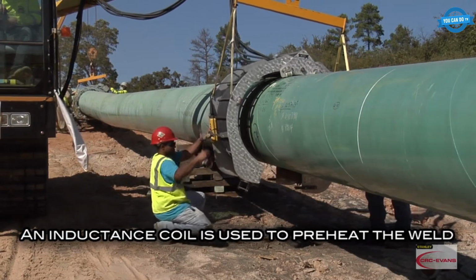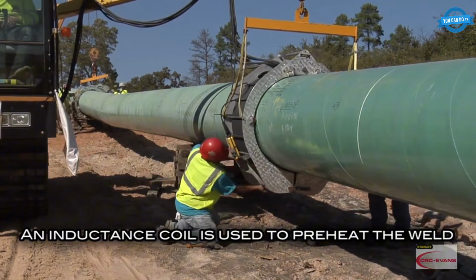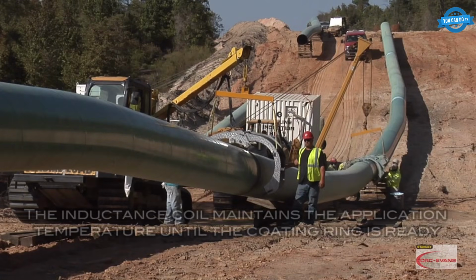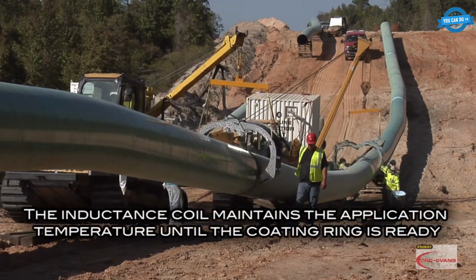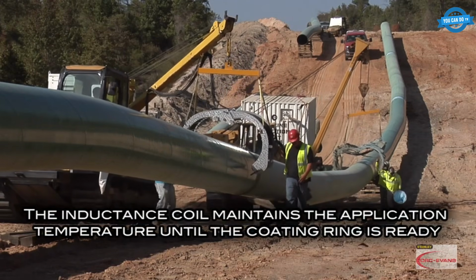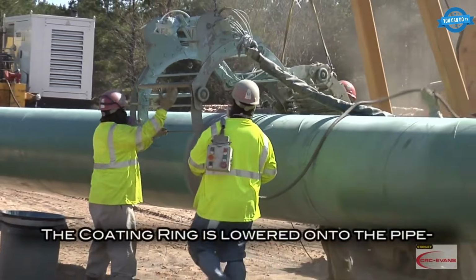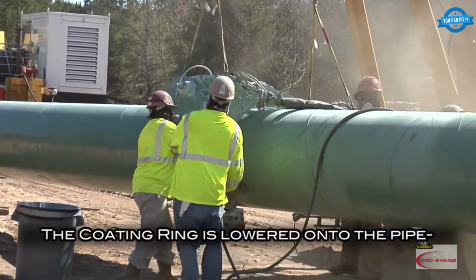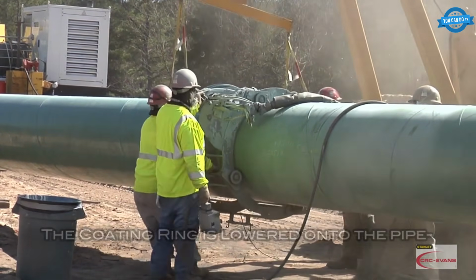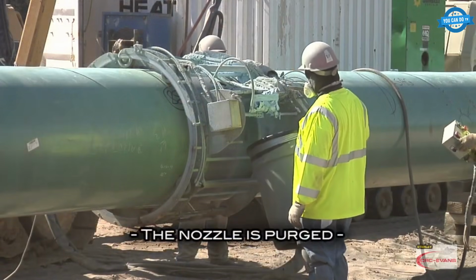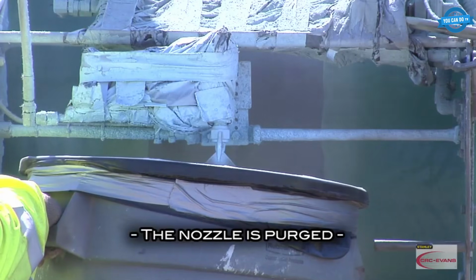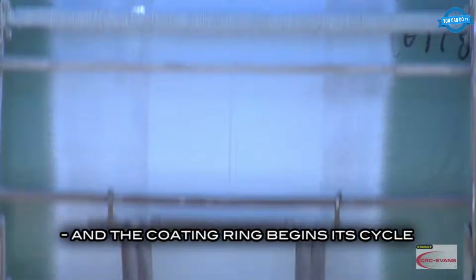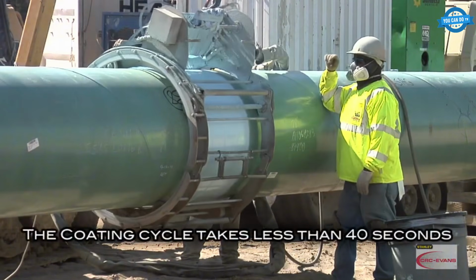At each joint on an overland route, the coating system runs through its cycle. The oxidized weld area is sandblasted to bare metal. An induction coil is placed around the joint and preheats the steel to coating temperature. A coating ring is lowered into position around the pipe. The nozzles are purged. The ring rotates around the joint and sprays a multi-component liquid coating evenly across the surface. The full cycle takes under 40 seconds.